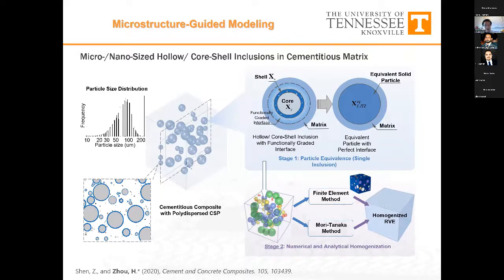But essentially, what we look at here is anything that's being added to a cementitious composite, as long as it's in a core shell configuration. It does not have to be spherical. It can be some other shapes, actually including fiber as well, where it has, like we said, a functional core and a shell. We found there is an analytical approach that we can do the conversion from that configuration to an equivalent property in that domain. Then we can use homogenization methods to calculate the equivalent properties, whether mechanical. In this case, what we have studied so far is mostly elastic properties, as well as thermal properties, including thermal energy storage and thermal conductivity, as well as electric conductivity and so forth.